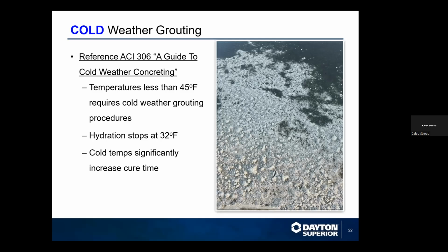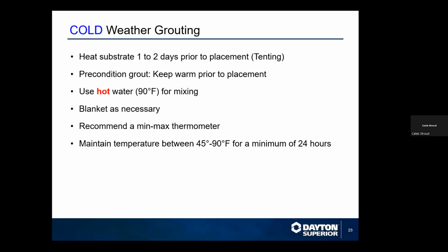And in the Dayton portfolio, we do have a cold weather grout that we'll talk about a little bit later, but it's a super high performance grout. And then also in guidelines with cold weather grouting, make sure you heat the substrate 1 to 2 days prior to placement, or you can tent it. Precondition your grout. Make sure you keep it at, I would say probably 70 degrees or higher. Use hot water for mixing and placing, a blanket as necessary. It's always recommended to use a min and max thermometer, and maintain the temperature between 45 and 90 degrees Fahrenheit for a minimum of 24 hours.